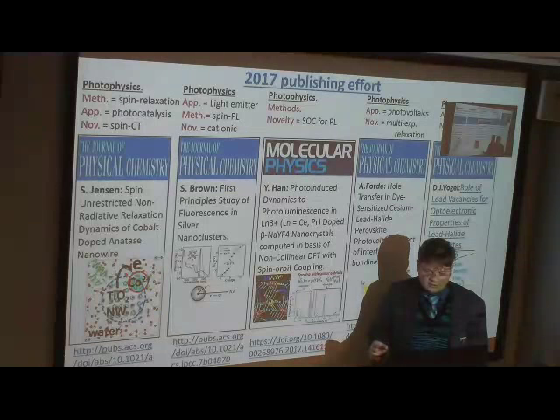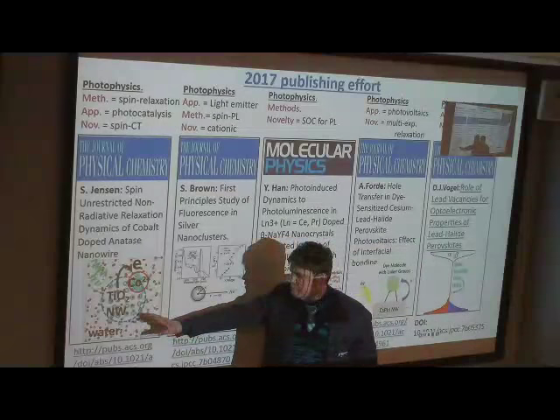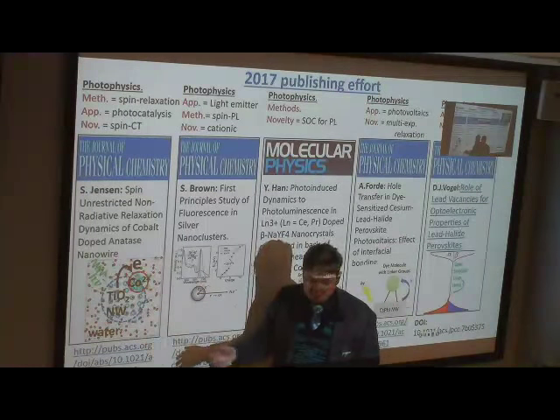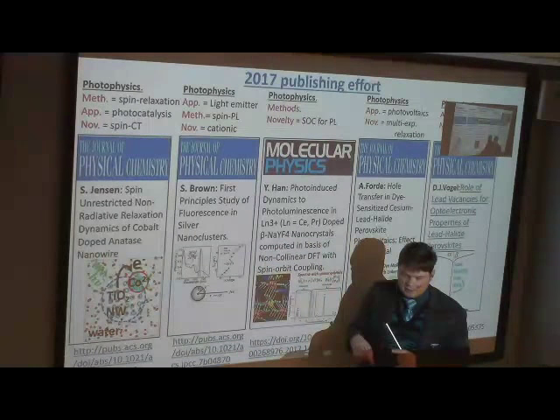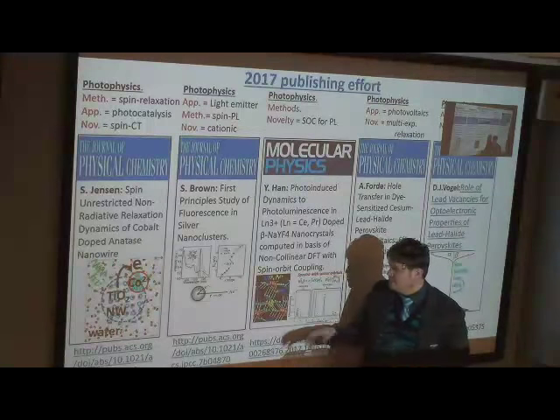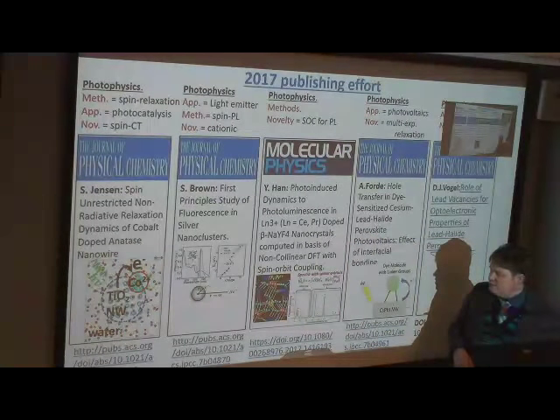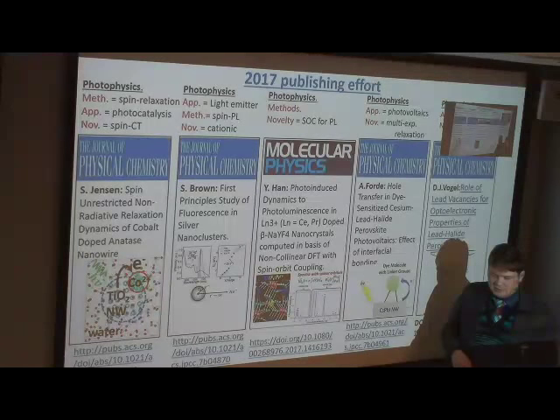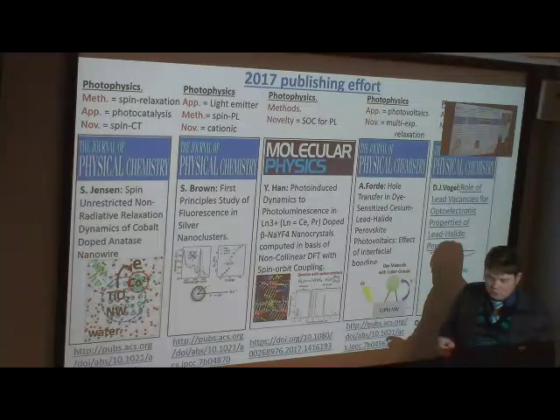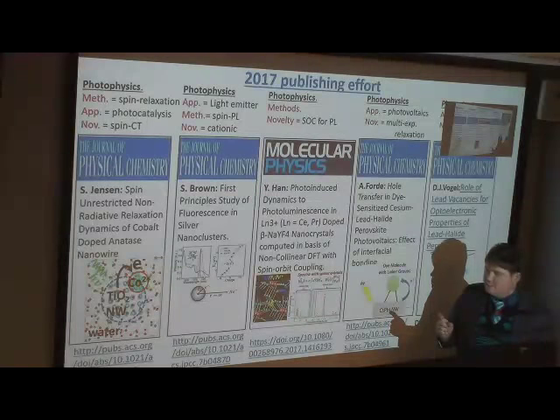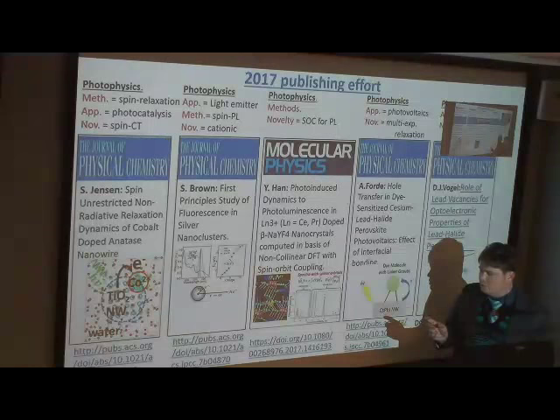For example, if it is an oxide with a balanced number of metal and oxygen atoms, one doesn't need spin polarization. Then the code was updated for spin polarization, when there are independent properties of electrons with different spin quantum number, alpha and beta. The next, critically important step is an update of the code for quantum dynamics for the situation when spin is not a good quantum number, when there are heavy elements that include occupied orbitals with high orbital angular momentum. In these situations one cannot get trustable results from a spin polarized model. There one uses so-called non-collinear spin.